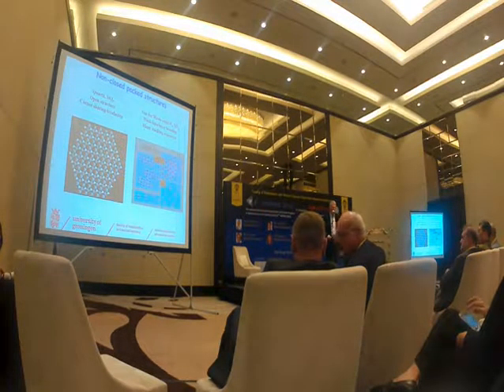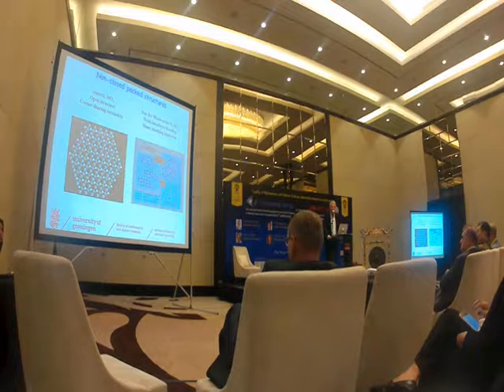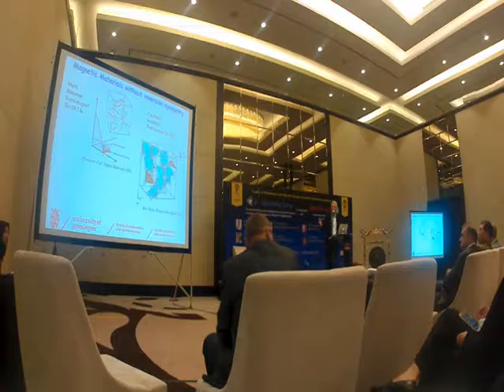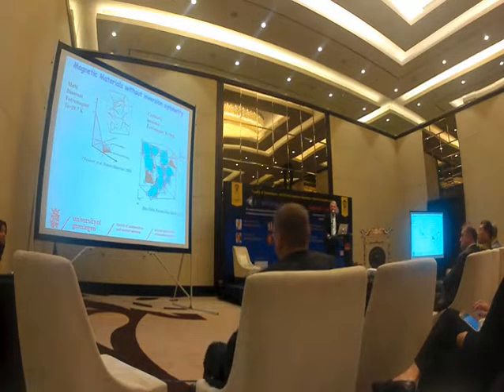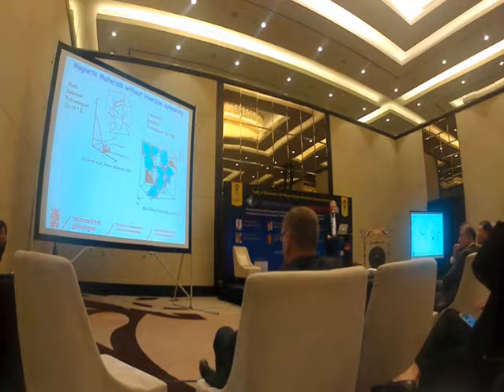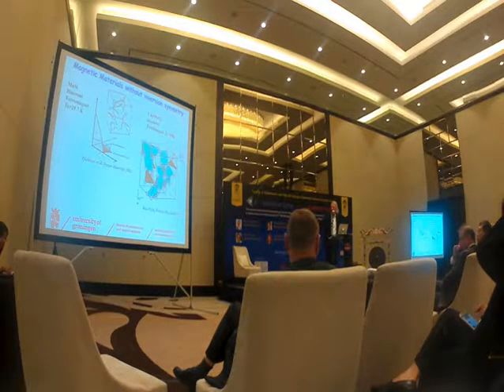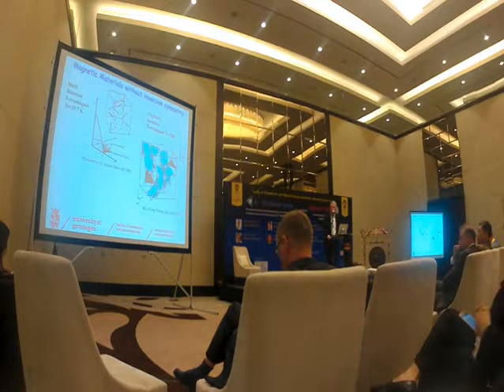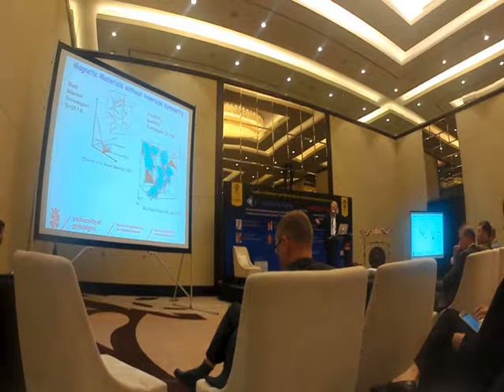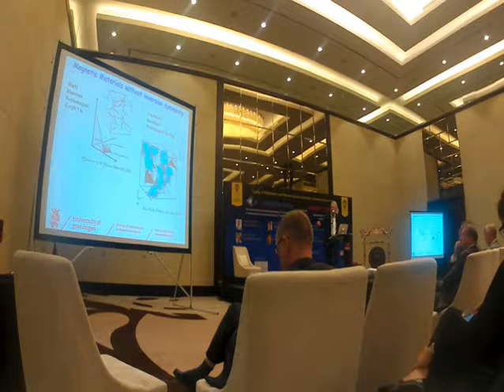So basically, the challenge that we have is to make materials that lack inversion symmetry. There are only few, or in our case only two. I mentioned previously manganese silicide, and the material that we rediscovered a few years ago is based on selenides, where the selenium takes the position of silicon for this tetrahedral coordination. This tetrahedral coordination gives rise to the lack of inversion symmetry, and this means that we now have two classes of inversion symmetry-less materials. One is manganese silicide, which is still a metal, and this is an insulator that can be used for dissipationless transport of information.